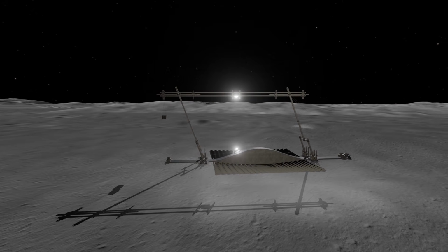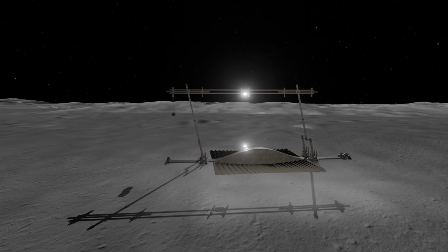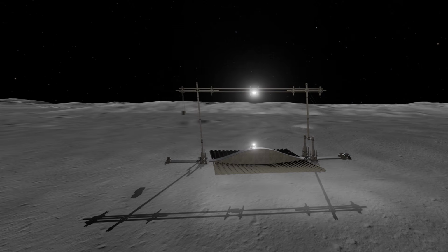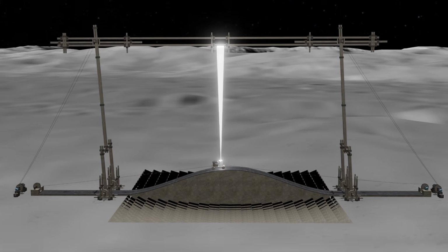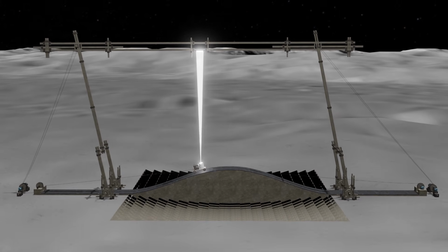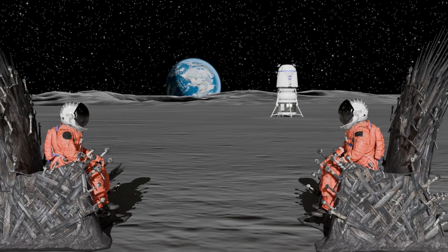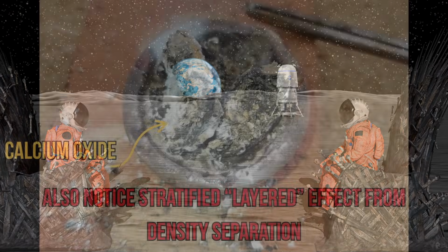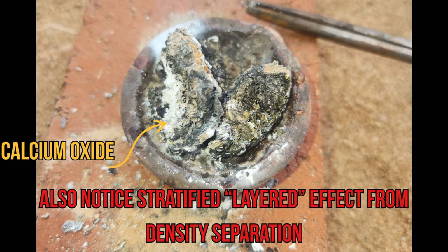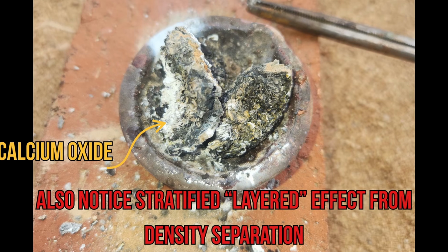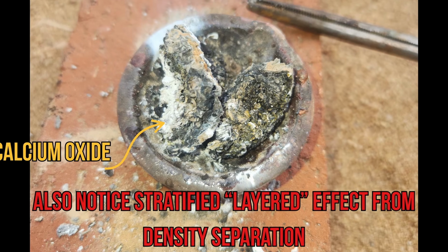Using that as your working medium to remove heat from a system, you can pretty much have almost like a conveyor system, or if not, a vibrational system, where it's a non-stop process, at least during the lunar day while there's sun. And then we got somewhat of a natural slag separation where the alloy cake separated from the calcium oxide and the silicon. Where the calcium oxide and the silicon were bound together though, right?